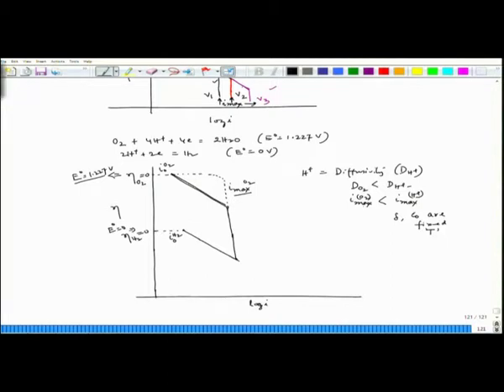So, if I look at only the hydrogen polarization part, without considering the oxygen polarization, it will have its own polarization and then finally reach its I max for H plus. The curve pattern would be, since the polarization starts from a higher potential from oxygen reduction, it will fall like this. If I draw it with a different color, this particular fall would follow this pattern, then switch to this pattern and then follow like this. So, these red lines would be the actual polarization line for both the reactions.